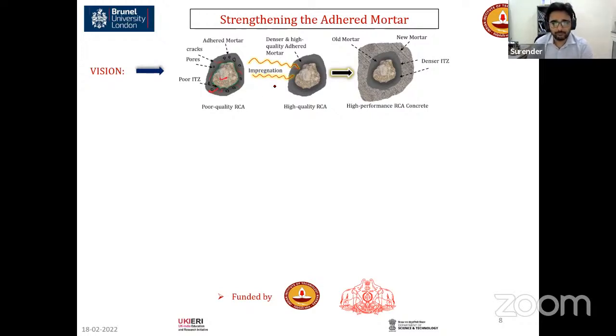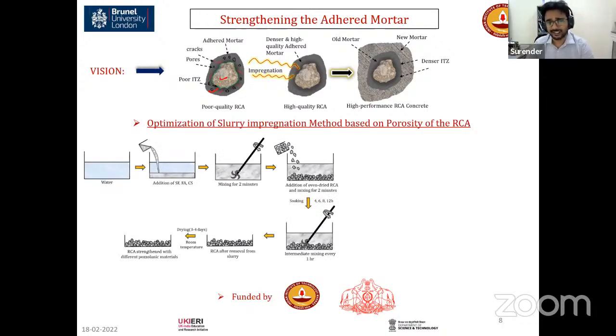So what we are doing, we have different techniques available to do it, right? One of the most important and highly promising techniques that you can use for large scale applicability in the field is the slurry impregnation technique, wherein different cementitious materials are mixed with water, and then the recycled concrete aggregates are soaked in it for different durations. After that, we take it out and dry it, and then we can use it. But this slurry impregnation technique is initial work, so we are right now optimizing it because the porosity